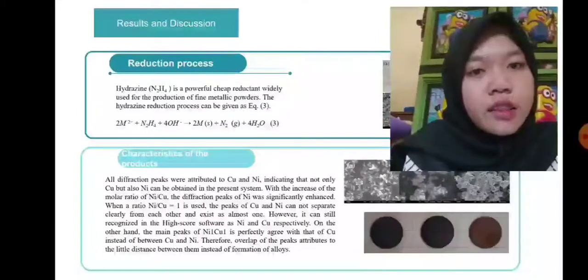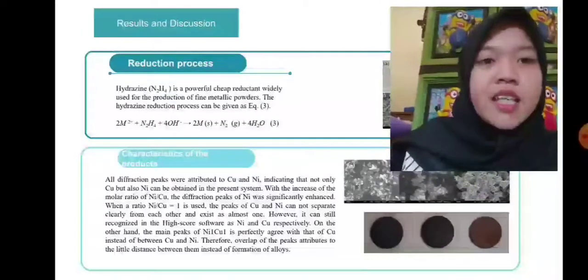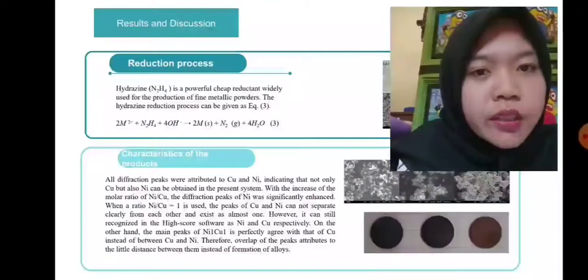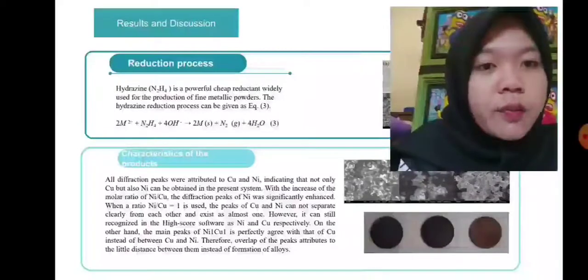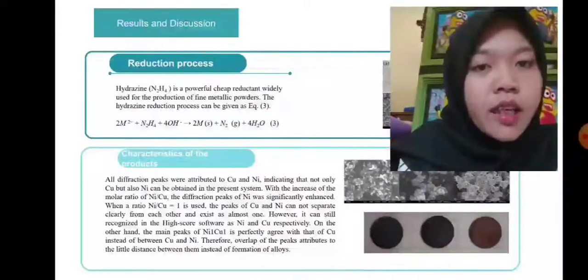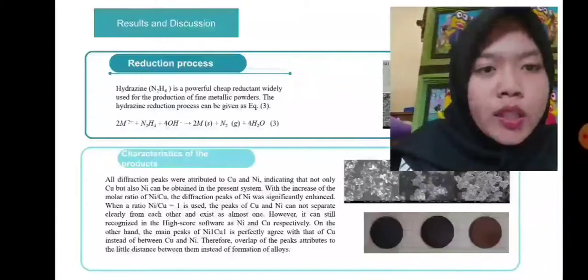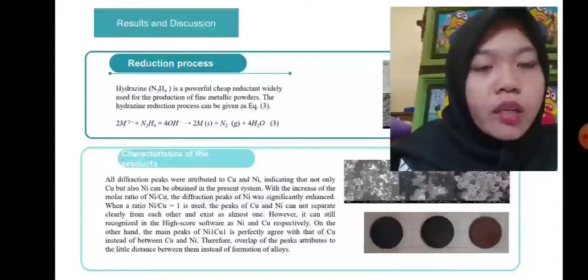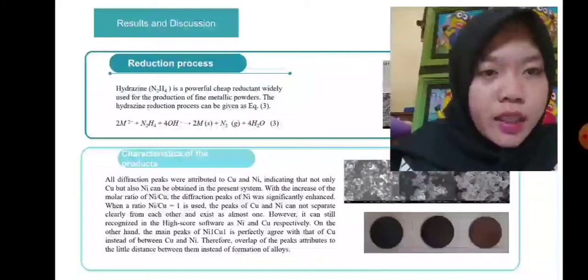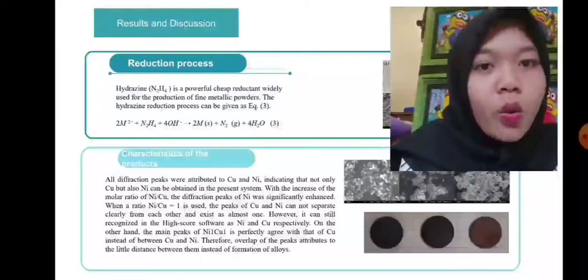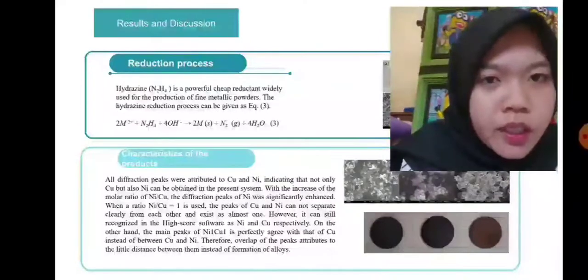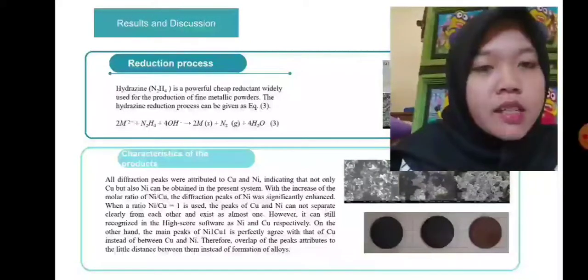And second, characteristics of the product. All diffraction peaks were attributed to copper and nickel, indicating that not only copper but also nickel can be obtained in the present system. With the increase of the molar ratio of nickel to copper, the diffraction peak of nickel is significantly enhanced. When a ratio of nickel to copper of 1 is used, the peaks of copper and nickel cannot be separated clearly from each other and exist as almost one.